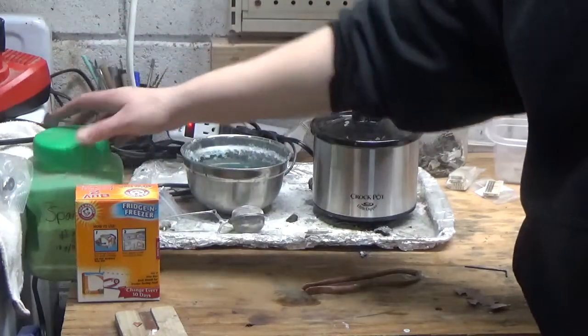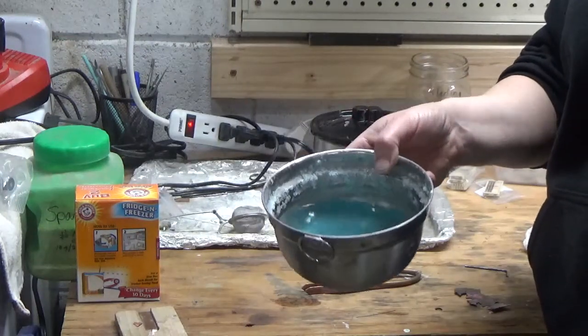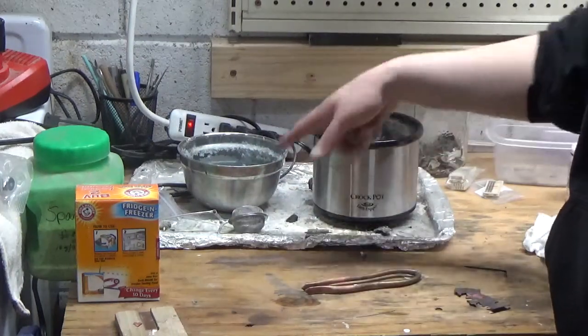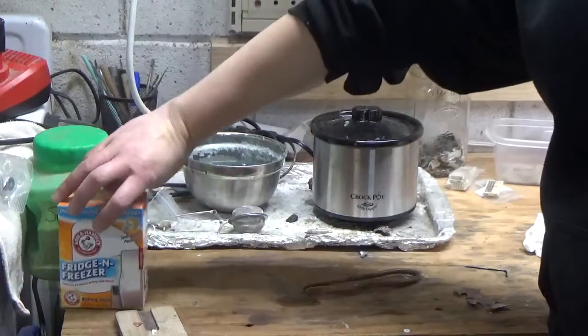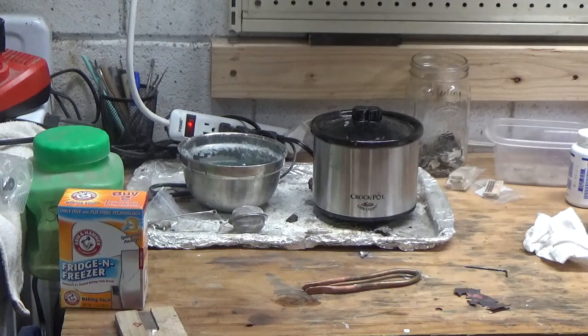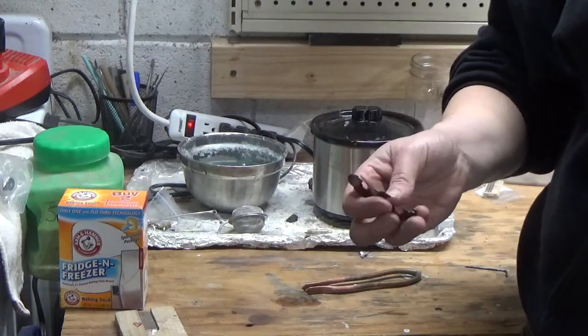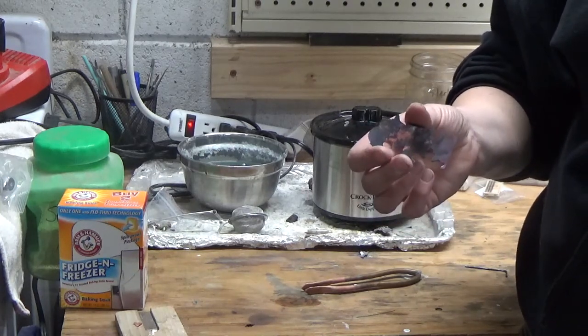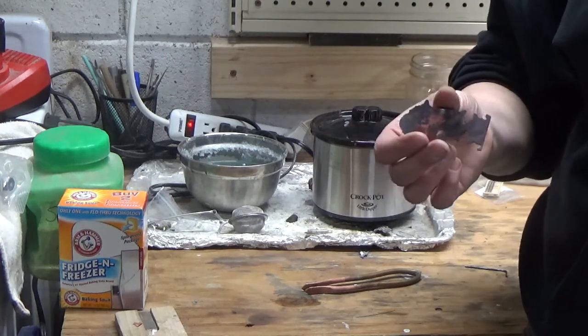The other thing you're going to need is a bowl — I have a metal one but you can use plastic — with water and baking soda in it. That's what it looks like after it's been used, and it's fine as long as it still fizzles when you drop something from the pickle pot into it. What the pickle does is it doesn't just get rid of your fire scale, tarnish, or any of that — it will also get rid of flux. As you flux a piece, you'll notice it leaves a glassy blue-green film. The pickle will eat the flux right off.